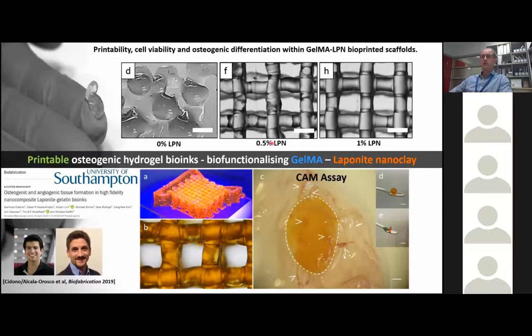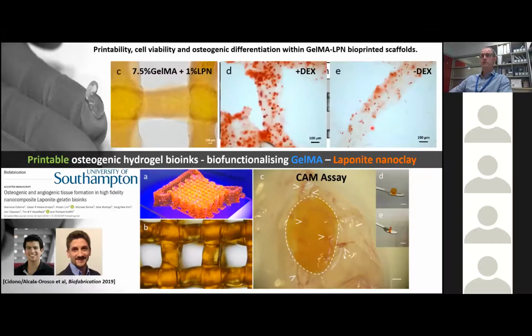So like before, we were able to come up with an optimal concentration of laponite, which allowed us to have printability, that we can then also show that in the presence of osteogenic differentiation factors, dexamethasone, we can get differentiation. And again, as an interesting side note, in the absence of some of those different osteogenic factors, we can also start to see nodule formation in some of our GelMA-laponite bioinks.